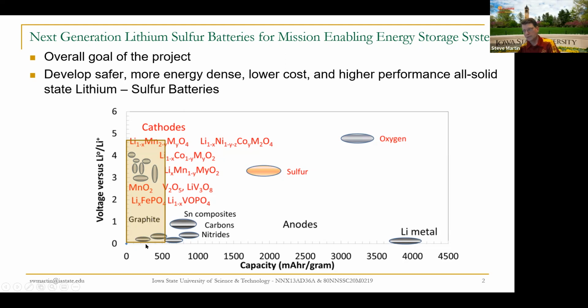And we think about that number as being low, although lithium-ion is much more energy dense than lead. It's low because the lithium has to be stored in graphite. It takes 6 graphite atoms to store 1 lithium ion, so low density there. And of course, with all these transition metal ions, you can see here 2 minus Y and Y. Even if X was 0, you'd have 1 lithium stored in 2 plus 4 atoms, maybe another 6. So that's 1 to 6, and it's just low density because they're just not lithium rich. Well, if you move out this axis a little bit to sulfur and react with sulfur, it turns out that 2 lithiums react with 1 sulfur.